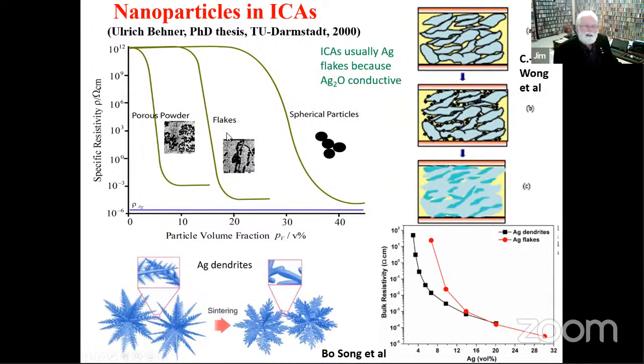So the idea then is, if this surface to volume ratio increase produced this change, then using nanoparticles, the people who did this called it porous powder, should produce a lower resistance again. So this is the idea here. Unfortunately, as you can see, the idea works in principle in terms of resistance for an amount of silver, but the resistance goes up at each step. And so this conducts with less silver, but at a higher resistance. So this was a good idea that didn't work particularly well.